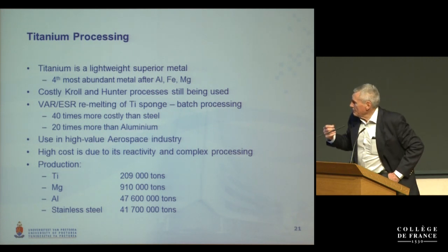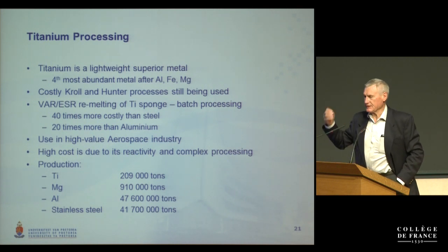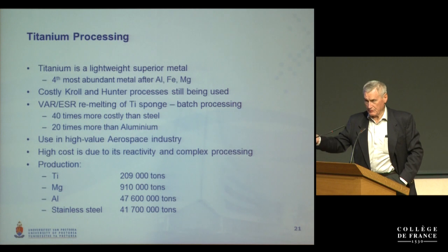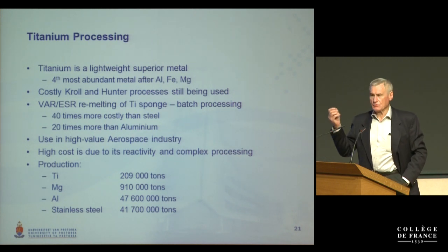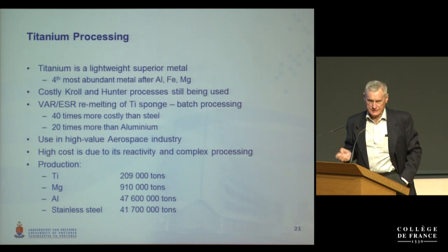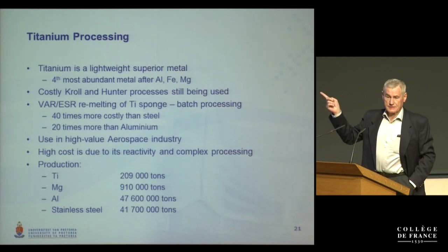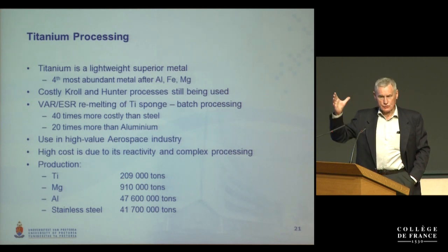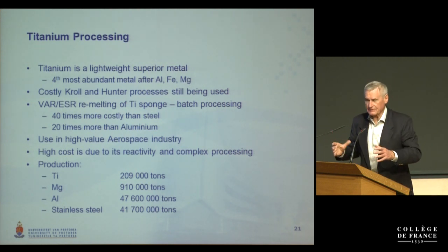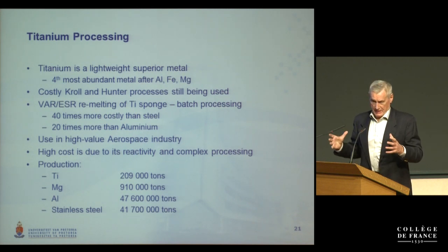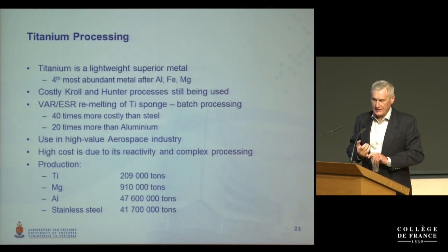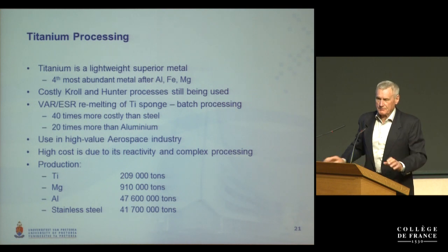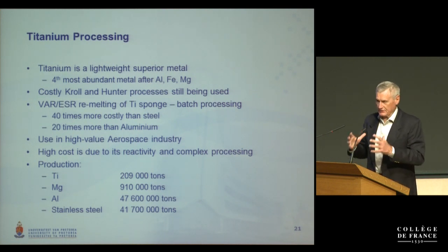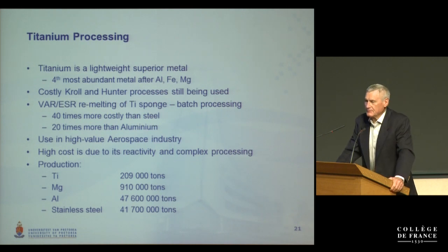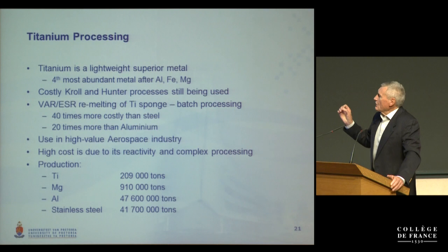So, although titanium is so superior in terms of strength, in terms of strength to weight ratio, and also in terms of its corrosion resistance, because all those silicate nickel leaching plants use titanium as the containment vessel to contain superheated concentrated sulfuric acid at 250 degrees with a pressure of 44 bars. They have to contain this. If it's not titanium, it's not possible. So it is really a